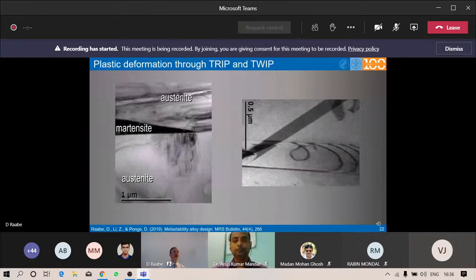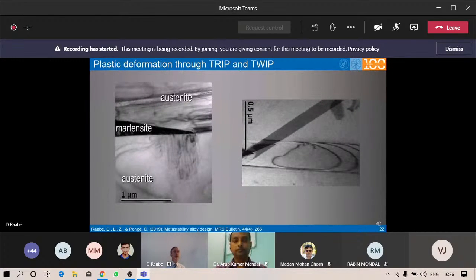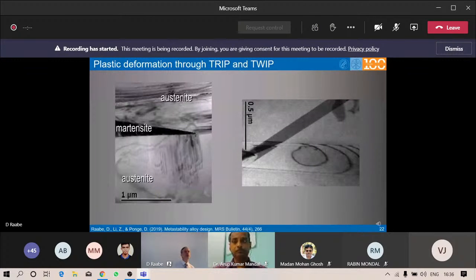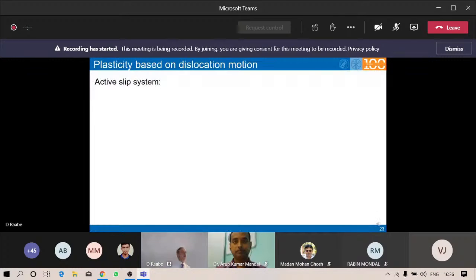Likewise, on the right-hand side, you can see here a typical in situ TEM image from a movie from a TWIP steel, where you see that the formation of twins produces a confinement of the plastic slip of the dislocations. And the hyperbolic function tells you that the stress for that half Frank-Read source operating here is scaling with the spacing of these twin walls. So these were just some examples where we try to translate elementary physical metallurgy mechanisms into corresponding mean field formulations, mainly through the reduction of the mean free path or the stress you need to activate Frank-Read sources.